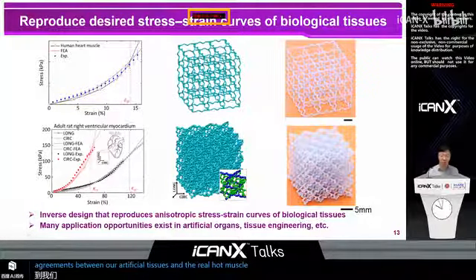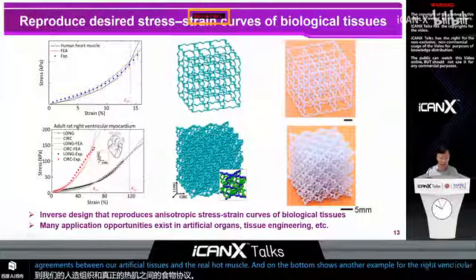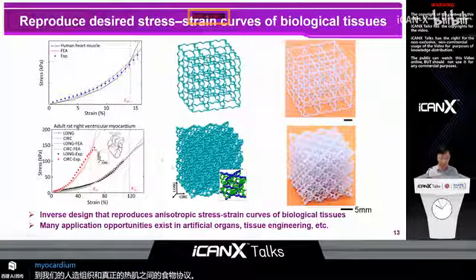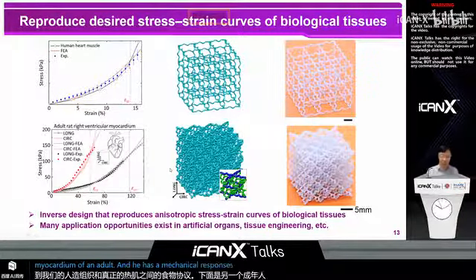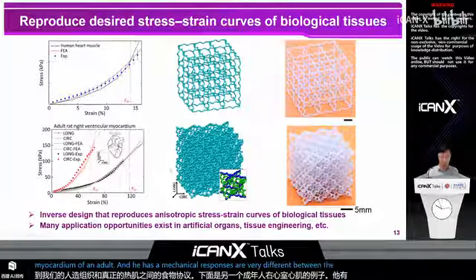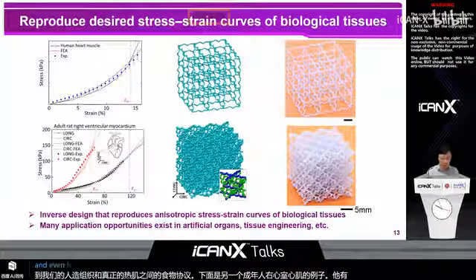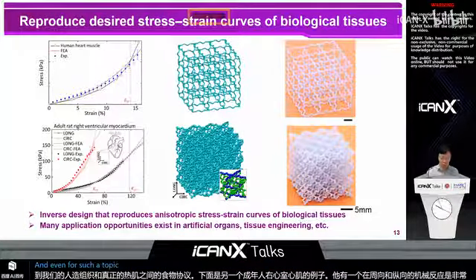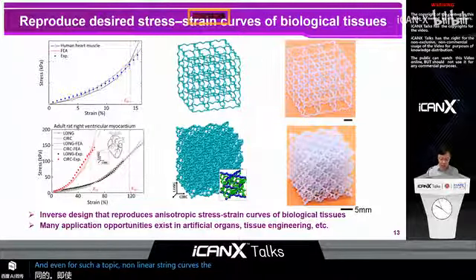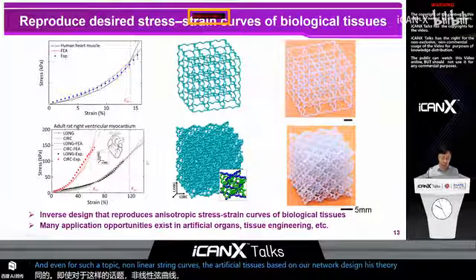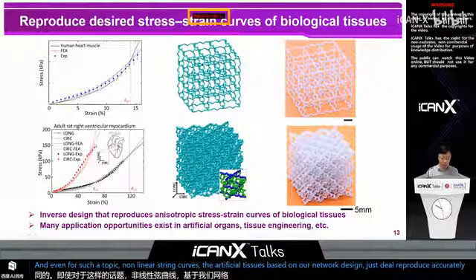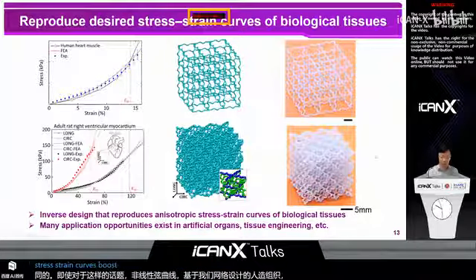And the bottom shows another example for the right ventricular myocardium of an adult rat. And here, the mechanical responses are very different between the circumferential and the longitudinal directions. And even for such anisotropic nonlinear stress strain curves, the artificial tissues based on our network design can still reproduce accurately the stress strain curves along both directions.